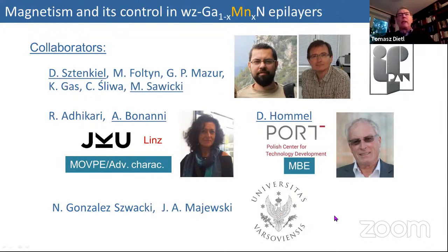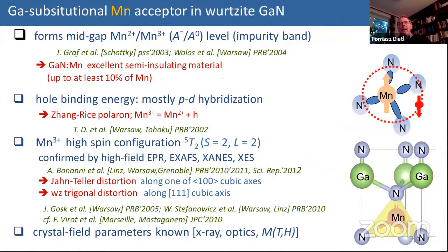And I'm going to present the work we have done with Darek Sztenkiel, Maciek Sawicki, also with Alberta Bonanni's group and the Hommel group. Alberta's group produced beautiful, advanced characterized samples by MOVPE. By contrast, Detlef Hommel and his team grew samples by MBE, which we have studied. And we also have a collaboration with the University of Warsaw concerning theoretical description of these materials. So, as I already mentioned, this is gallium nitride with manganese acceptor. It's an excellent semi-insulating material. We found that up to 10% of manganese, this material does not conduct.